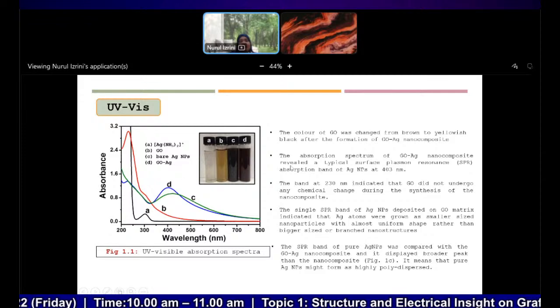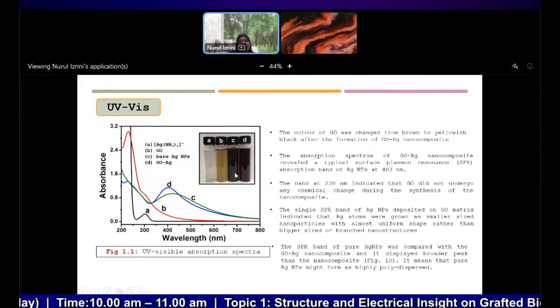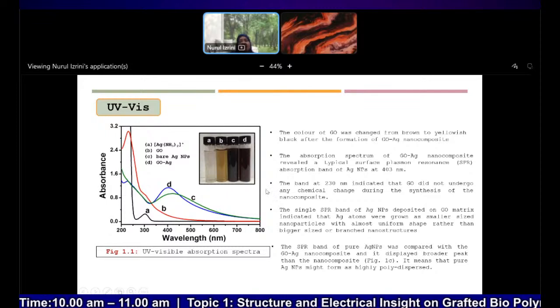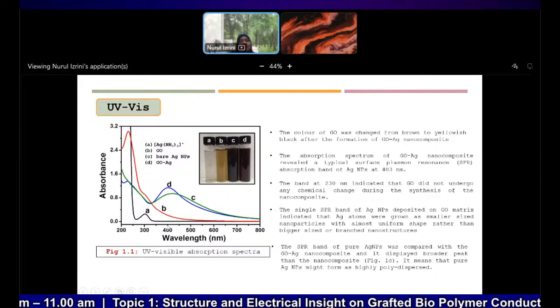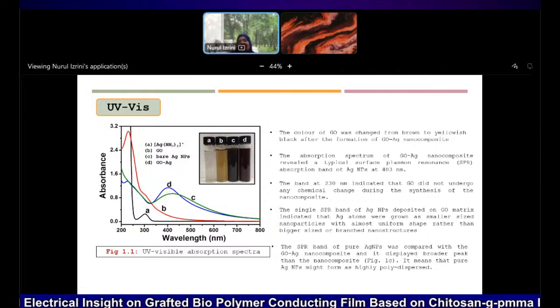The absorption spectrum of GOAG nanocomposite reveals a typical surface plasmon resonance absorption band of AG nanoparticles at 403 nanometers. We can see a very nice sharp peak for GOAG, which is attributed to the AG nanoparticles. So we can first confirm with UV-Vis that the AG nanoparticles formed on top of our GO sheets.